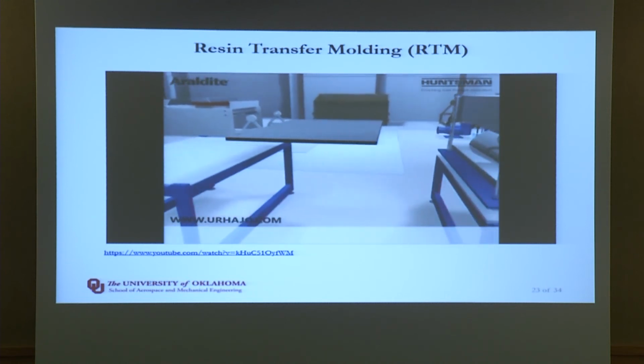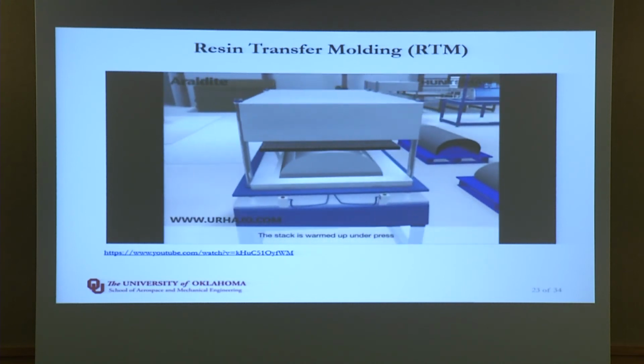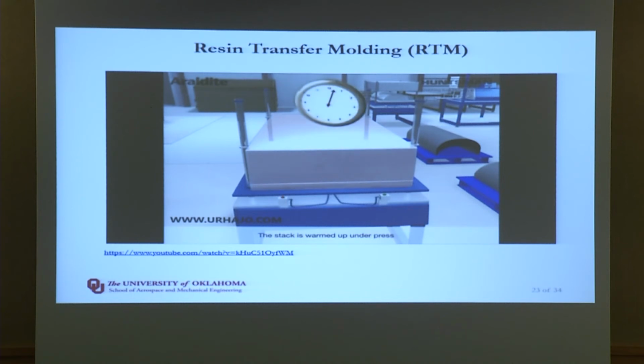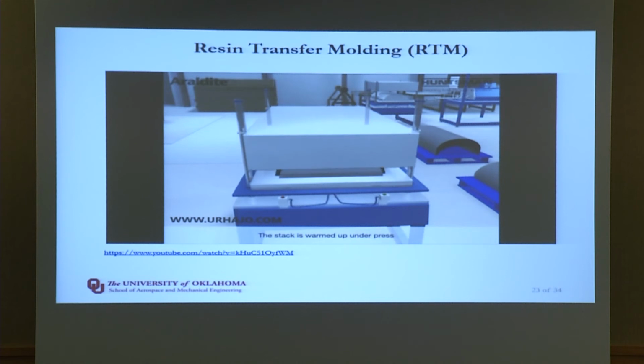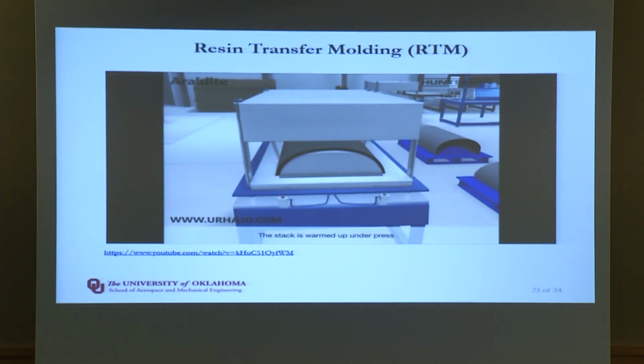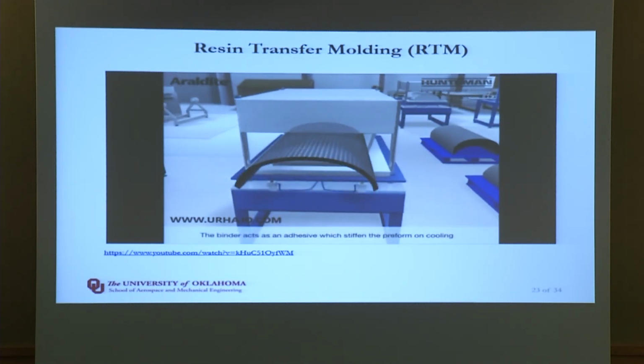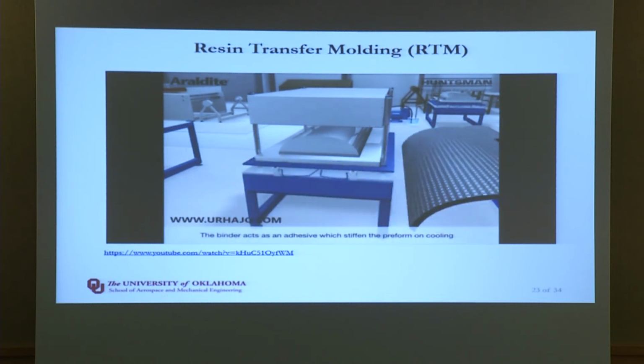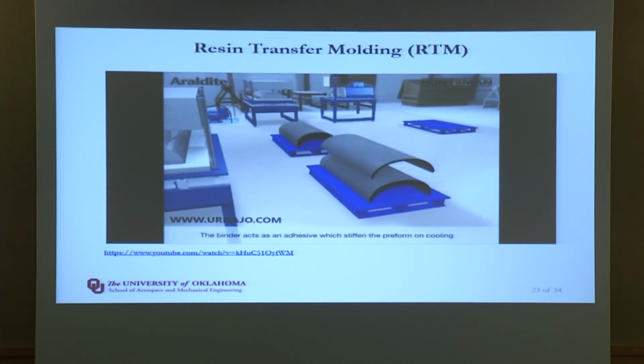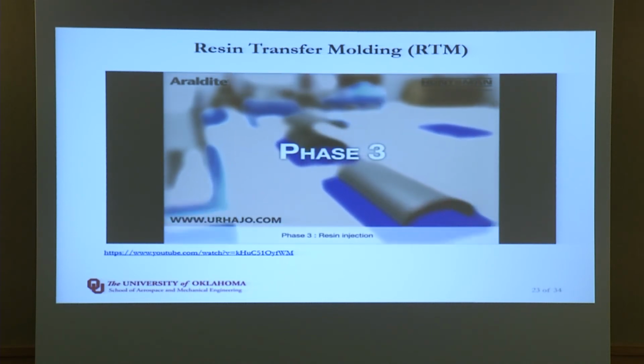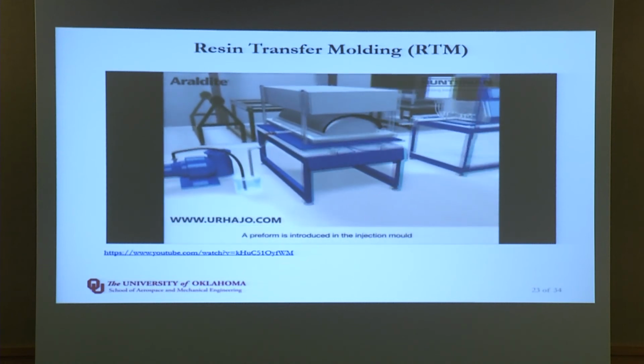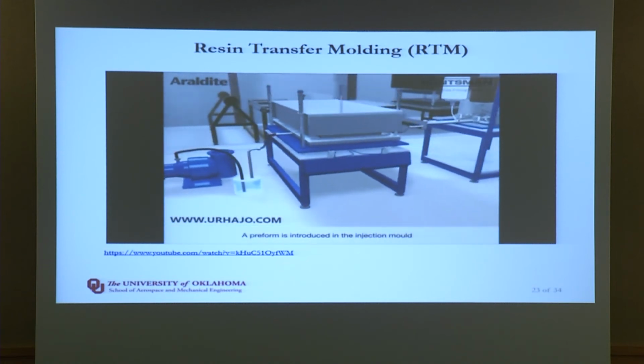You then take these and put them in some sort of press to warm them up. Apply some sort of compaction pressure, but this is just to give it the shape, you are not wetting, you just bend it, heat it up a little bit. The layers have mechanical contact, you press the fabric against each other, therefore they come out in one single piece, and then you essentially stiffen. It becomes not too stiff but easy to handle. Then you take these parts to the mold where you inject the resin.